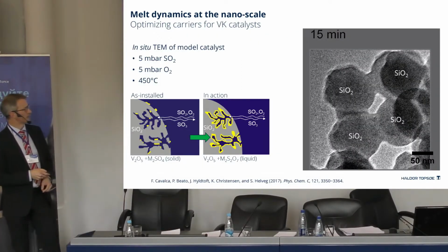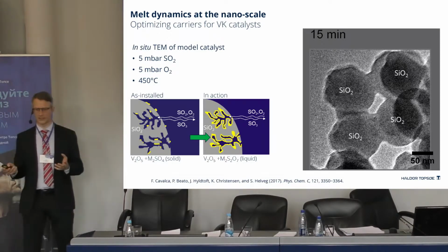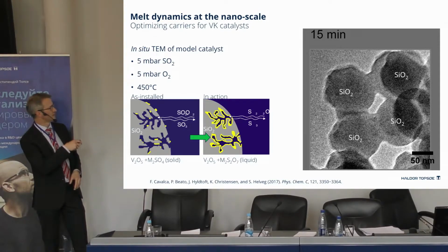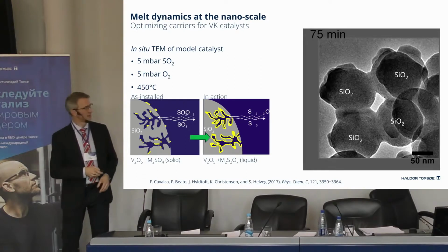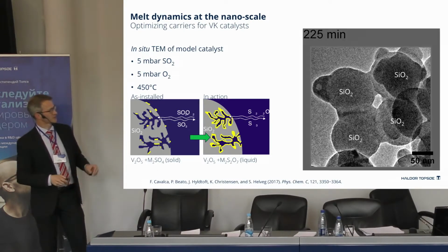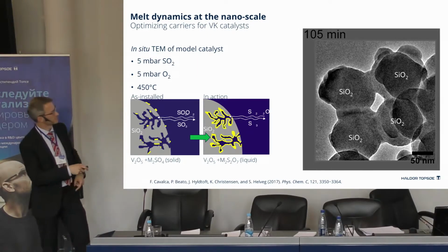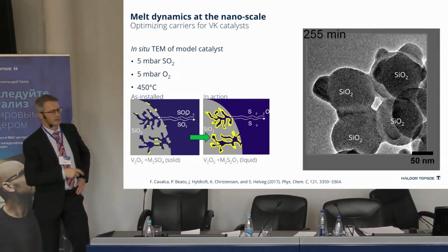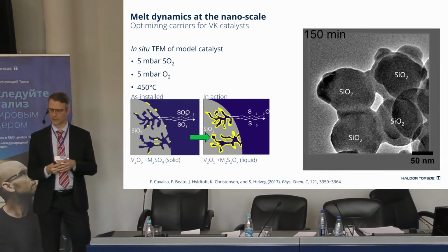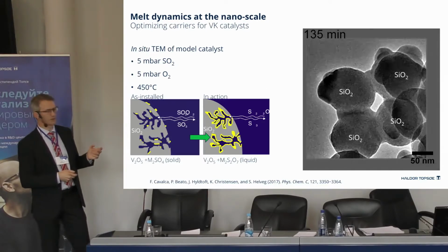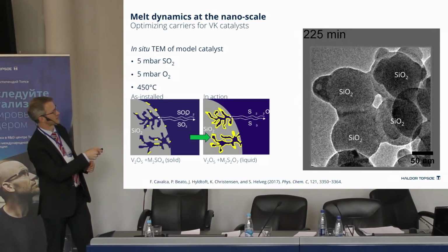So here's one example where we put in a catalyst with 5 millibar SO2 partial pressure, 5 millibar oxygen, and we put it in at 450 degrees, and we'll see what happens from the as prepared catalyst to when it's put on stream in the microscope. And let's see if this works. So here you can see it as a function of time what happens on the nanoscale. And one thing to observe is that in the cavities between the silica particles, the melt seems to accumulate, which makes sense because it's the capillary action taking place to redistribute the melt. But another thing that we didn't expect was that on the convex surfaces of the silica, we see something else building up, and it seems to form some faceted particles instead. So clearly there's something different in the convex and concave areas of the catalyst.